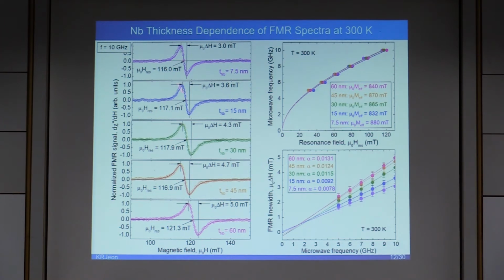As the niobium thickness increased, the FMR peak-to-peak line width, directly proportional to the effective Gilbert damping, increased, whereas the resonance magnetic field associated with the effective saturation magnetization varied little. This implies that dynamic coupling across the permalloy and niobium interface efficiently transfers spin angular momentum from the permalloy into the niobium layer, which enhances the effective damping of precessing magnetization.